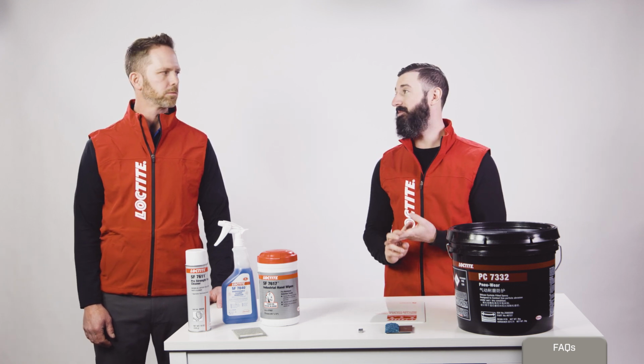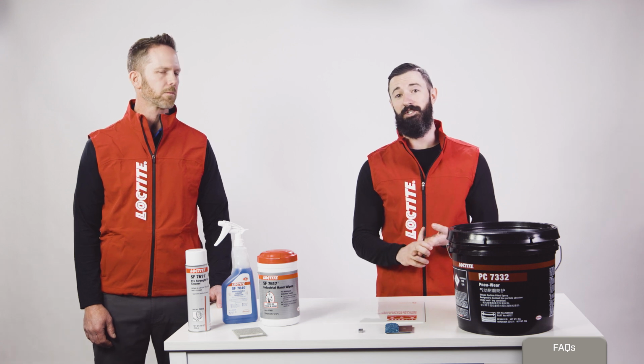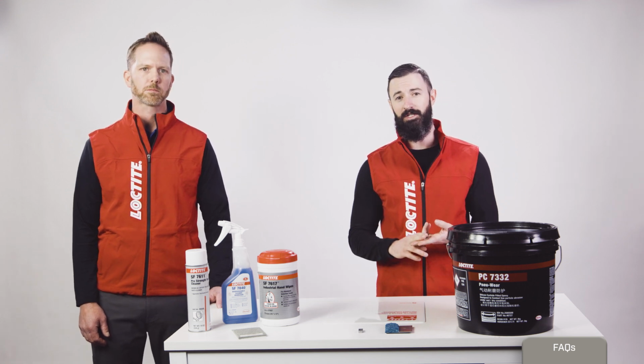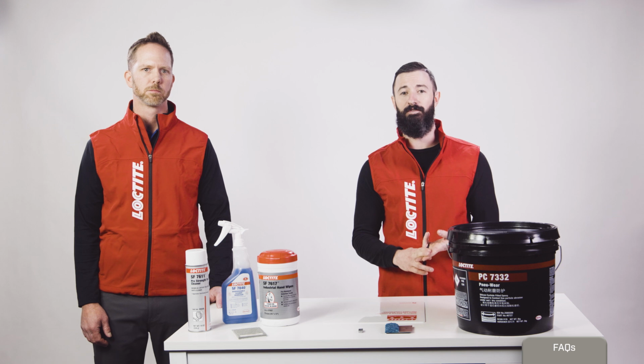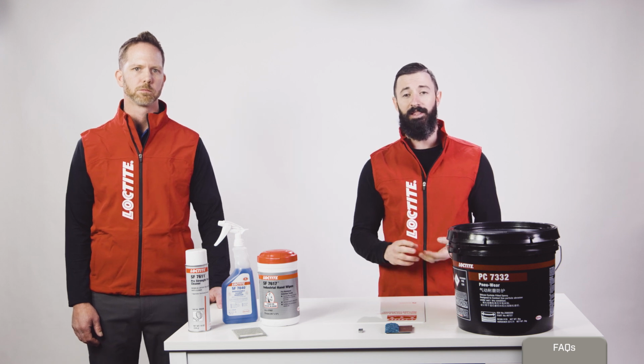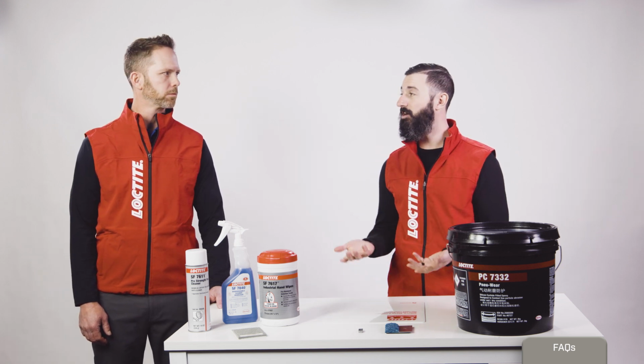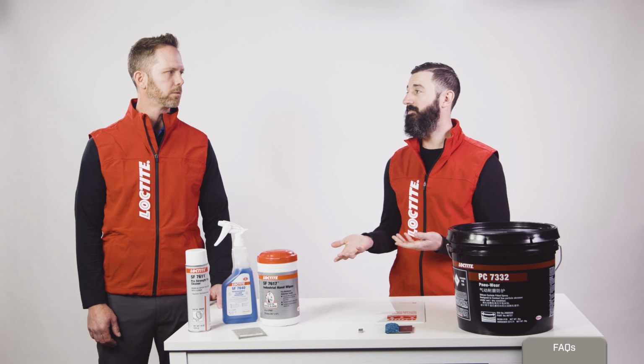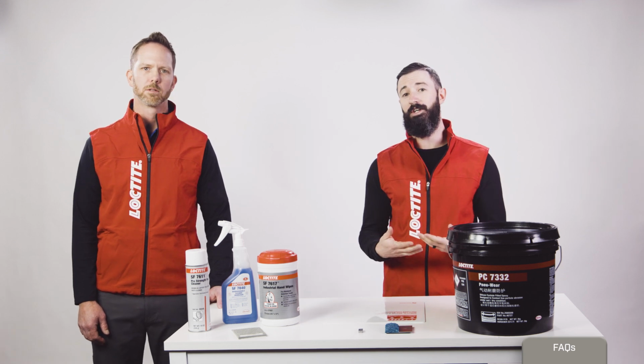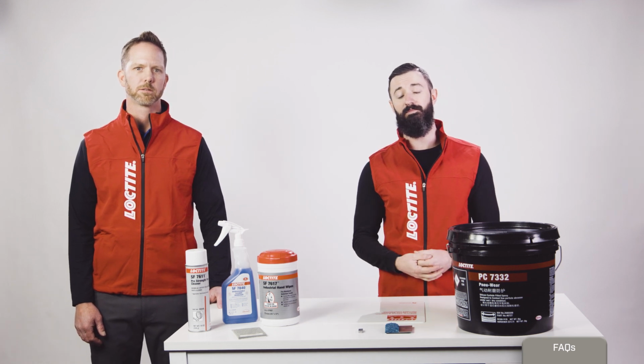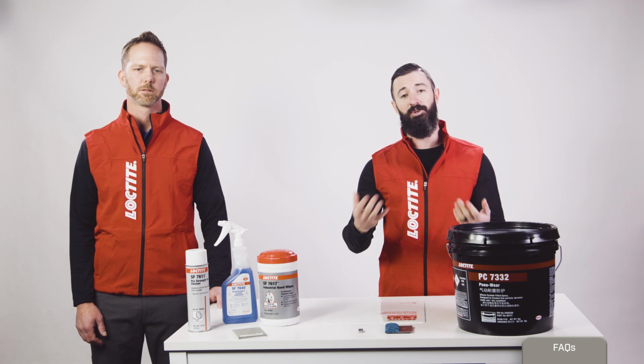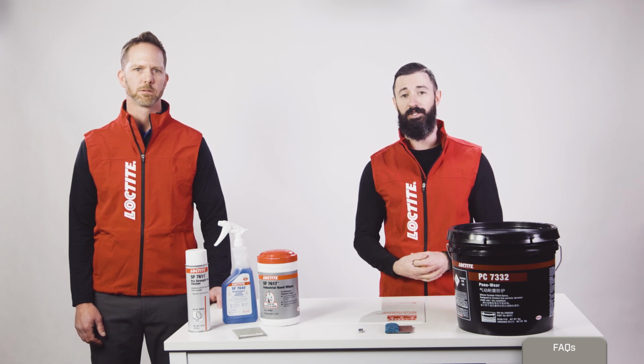The second step is the mechanical removal step that was also mentioned. This is something like grit blasting to remove rust and increase the surface area for the coating to adhere to. And then finally, that last step is the solvent-based cleaning with the Loctite SF7611 to remove all of the dust and any contaminants left over from the mechanical removal stage so that you have a nice clean and dry surface for bonding to.